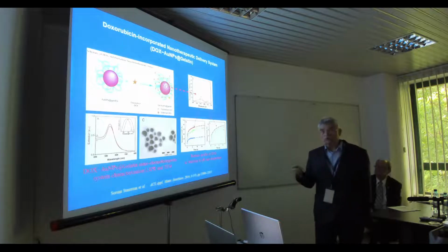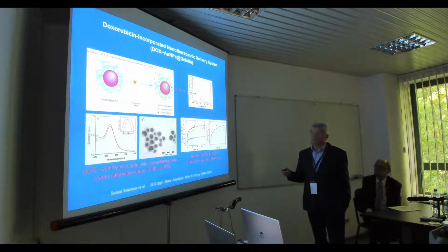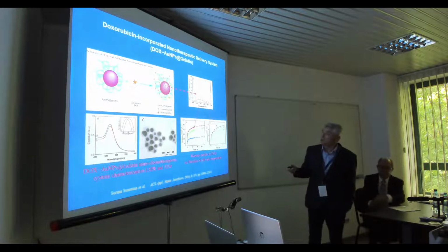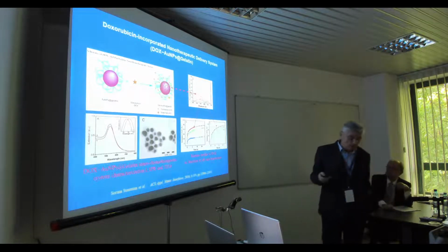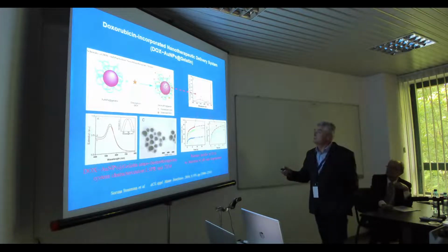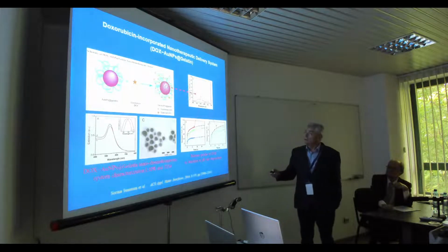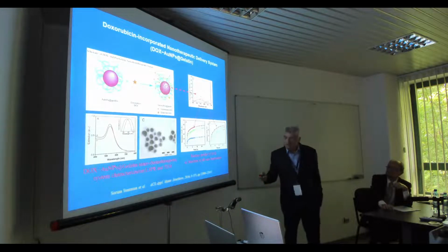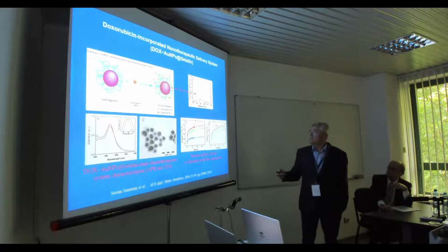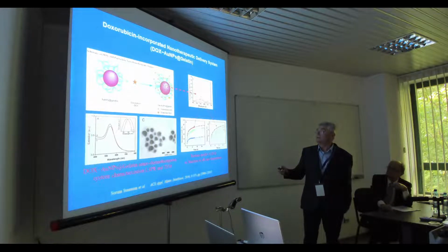And to control delivery, we modified the pH of the solution. This is known: in the cancer cell environment, the pH is more acidic. So it is true here. At neutral pH there is a degree of delivery, but it increases significantly for pH around 5.